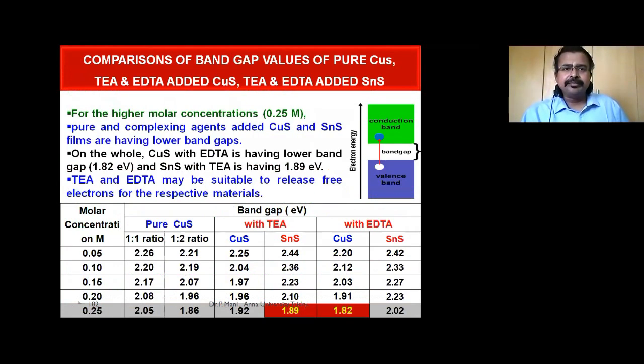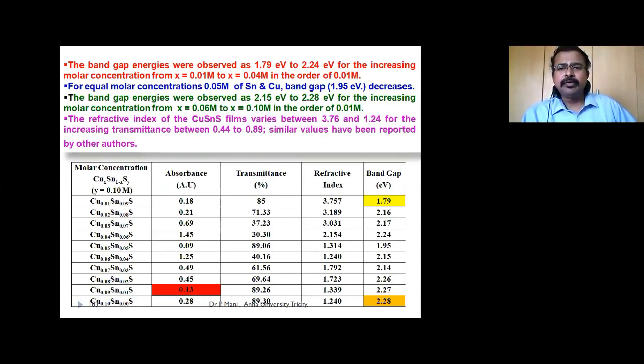Okay, here we are comparing the materials we have taken for pure copper sulfide in the ratios 1 is to 1 and 1 is to 2. Likewise, the band gap is ranging from 2.05 to 2.26, 1.86 to 2.21. And for TEA added copper sulfide and tin sulfide, it's ranging between 1.9 to 2.25. For tin sulfide with the TEA, 1.89 to 2.44. With the EDTA, both copper sulfide and tin sulfide: copper sulfide with the EDTA, 1.82 to 2.20. EDTA with tin sulfide is 2.02, right? And here we are seeing the minimum of 1.79 and the maximum of 2.28 electron volts.